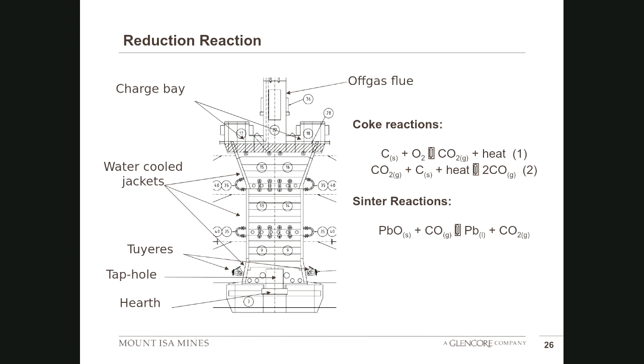So around here. And that reaction zone is basically the burning of carbon with oxygen to create CO2 plus heat, which then reacts with more carbon to create carbon monoxide. So that carbon monoxide flows up to the top, reacts with the lead oxide. That lead oxide is turned into lead droplets. That drips down like rain, goes down to the bottom, and then comes out into a forehearth, which then is